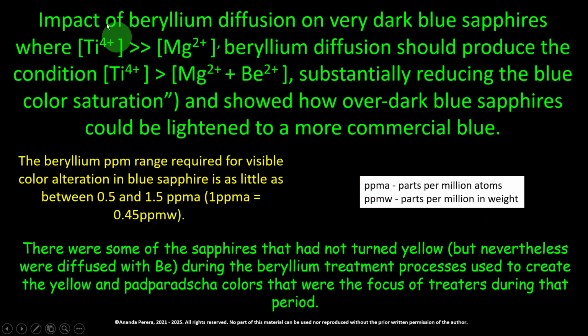Next thing is the impact of beryllium diffusion on very dark blue sapphires, where the percentage of titanium 4 plus is bigger than magnesium 2 plus. Magnesium is the smallest amount, titanium is big, then the beryllium diffusion should produce the condition titanium greater than magnesium plus beryllium. Then the smaller amount of magnesium ions joined with berylliums, but the amount is a little bit lower than the titanium percentage, substantially reducing the blue color saturation. Then it reduced the blue color saturation and showed how overly dark blue sapphires could be lightened to a more commercial blue.